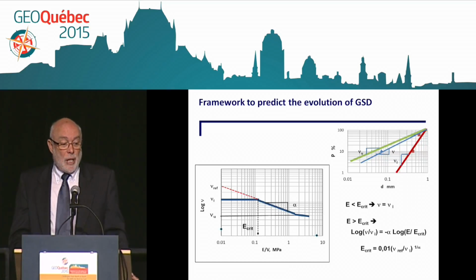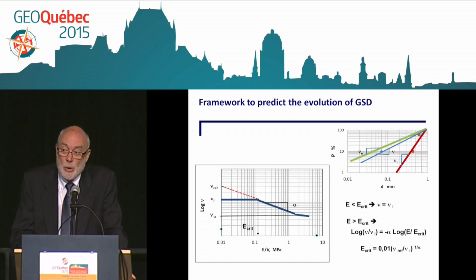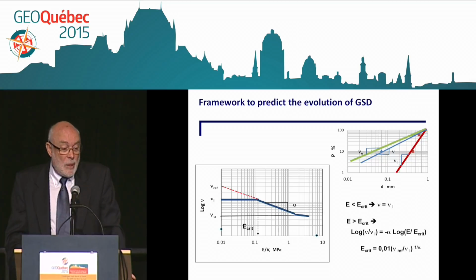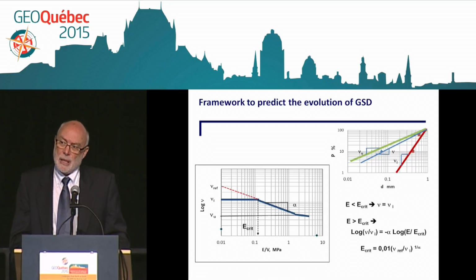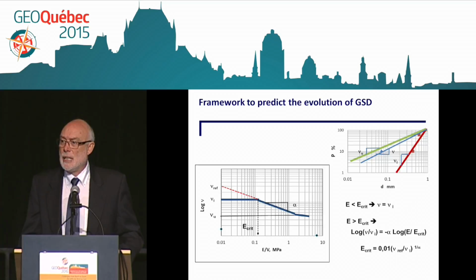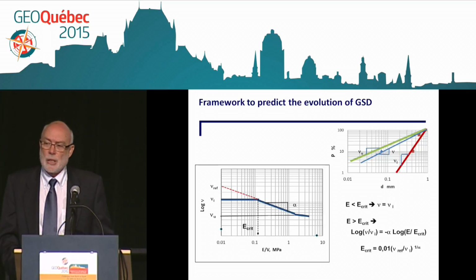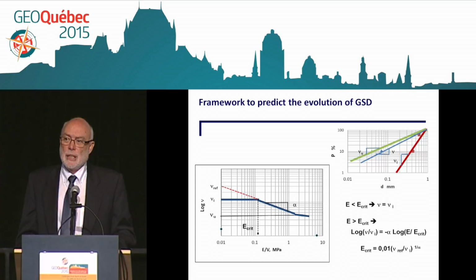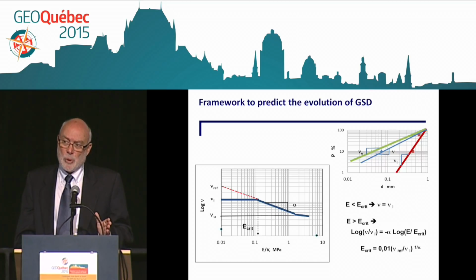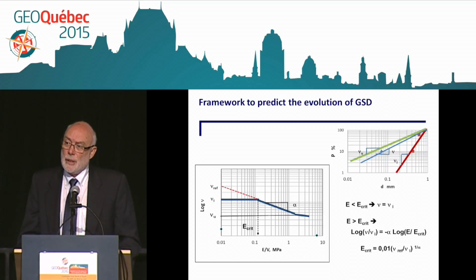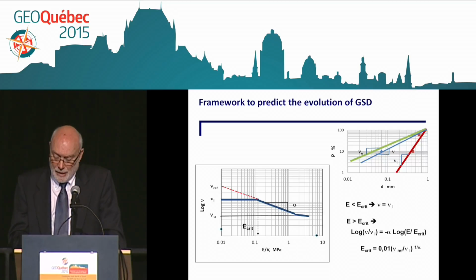So that's the framework that we propose to predict the evolution of grain size distribution. We have a plot of the log slope of the grain size versus input energy. And as long as the input energy is less than the critical input energy, there is no change in the grain size curve. That's an approximation. There is always change, but the change is not so significant. But once we input more energy than this critical energy, we're going to induce a significant fragmentation of the particles.